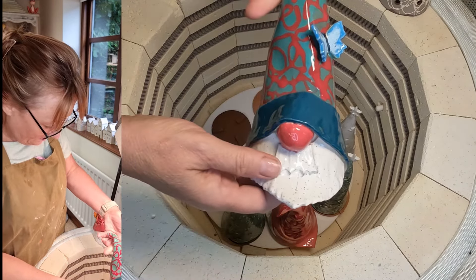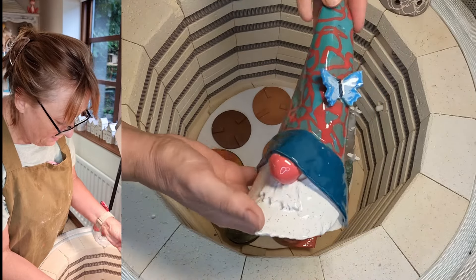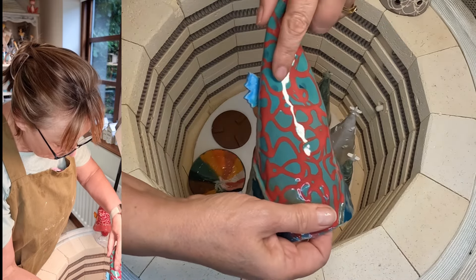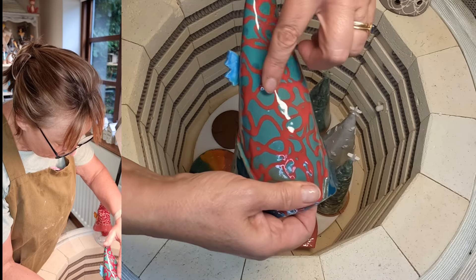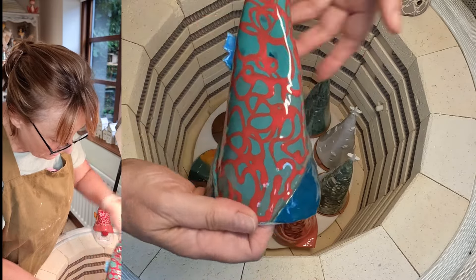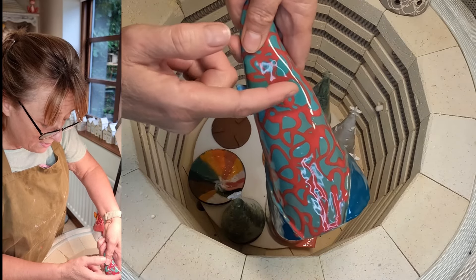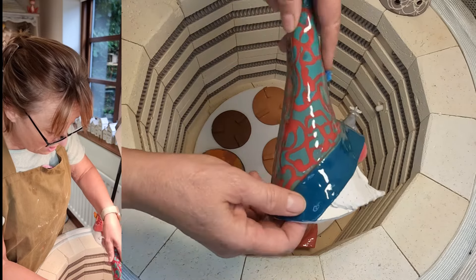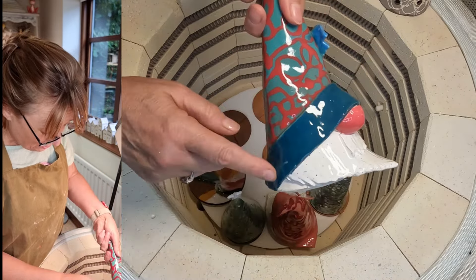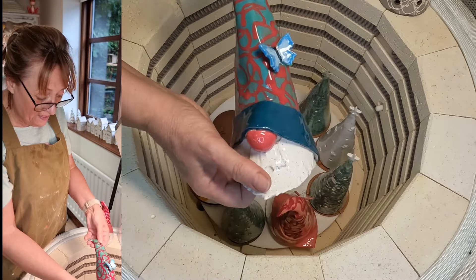So I chipped off as much as I could and ground down the rest. There was an incompatibility between the clay body, the clay slip and the terracotta, because I hadn't bisque-fired it - so it was a trial. I've basically reglazed them and it looks like it's okay. Actually, if I didn't tell you you wouldn't know! Mark's going to be so pleased with that. Underneath here there was some green with some dots, and where I've put the red over the top I can feel very slightly a ridge where I had to take off the glaze. You can see this is slightly more solid color where it's got the white slip underneath.